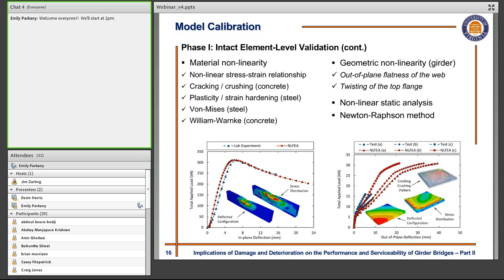In the other case, the reinforced concrete slab, our model was able to predict the elastic behavior up to almost 5 kilonewton of the applied load, which is the first cracking load of this structure. After that, we had a reduction in the stiffness, but there is a little bit of discrepancy between the numerical and experimental results, and that is mainly related to the limited information on the test setup, the test report, and also the boundary conditions used during the test. So we made lots of assumptions in our numerical model.